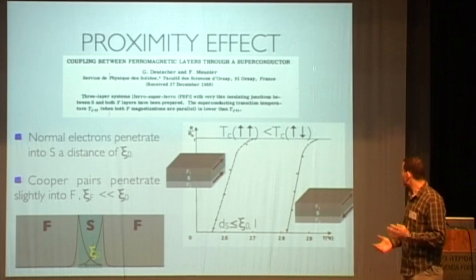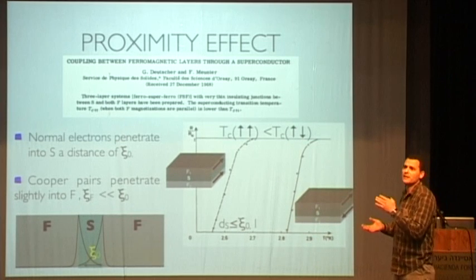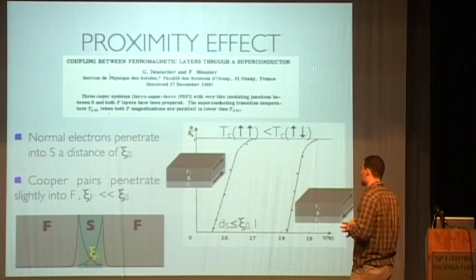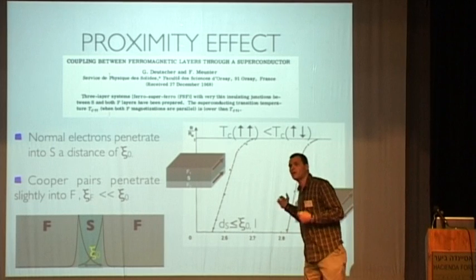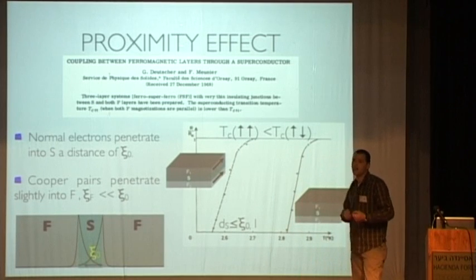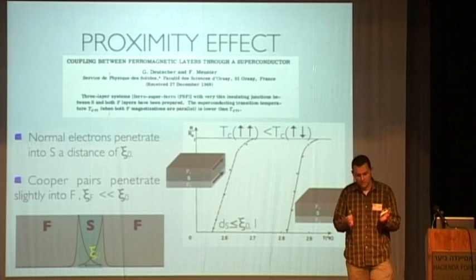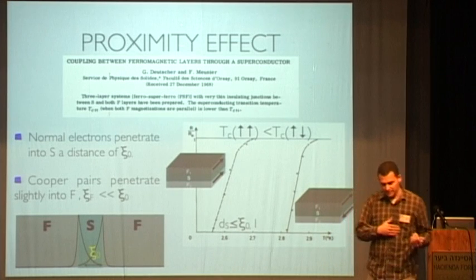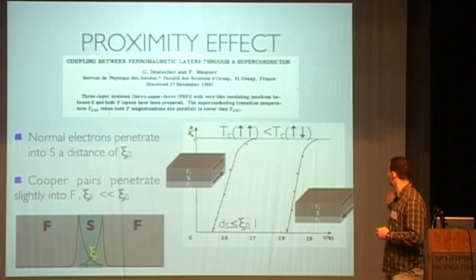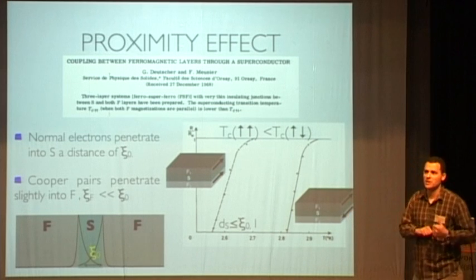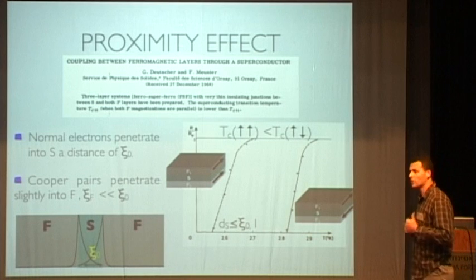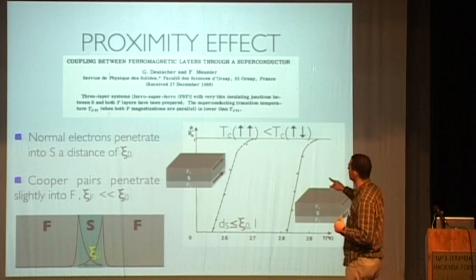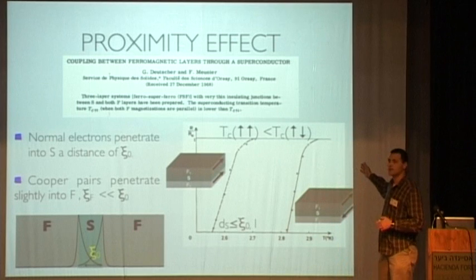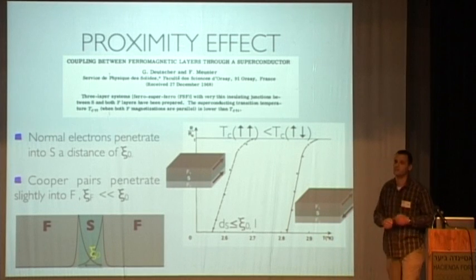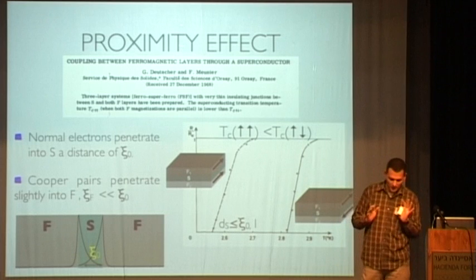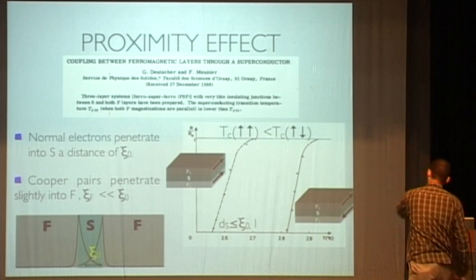And for example, here in an article 40 years ago by Guy Deutscher, they measured a sandwich of two ferromagnets and a superconductor in between. And the normal electrons, because they are polarized, destroy the superconductivity slightly, and they show that there is a difference between the anti-parallel configuration and the parallel configuration because of the normal electrons, which are polarized, which penetrate into the superconductor. They show the TC of the anti-parallel state is higher than the TC of the parallel state. So the concept of proximity is very important.